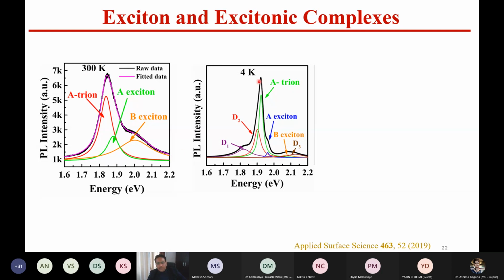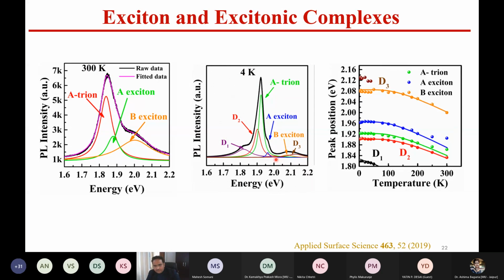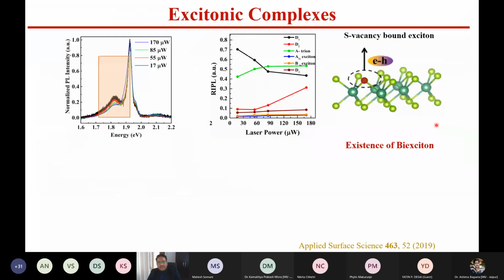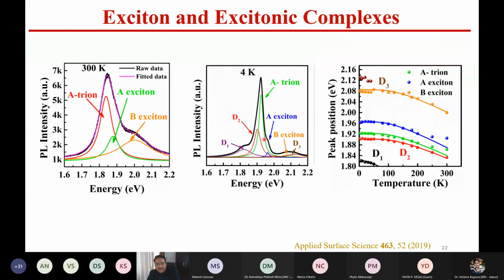But when we cooled down the sample to 4 Kelvin, we saw 6 different transitions appearing, and if we look at the temperature dependence of these transitions, the electron-phonon interactions are visible, but there are some peaks which lie only up to a certain temperature and then disappear. This is very interesting. Instead of 3 peaks, there are 4 going up to room temperature, and we tried to understand it. Let me go back here and tell you.